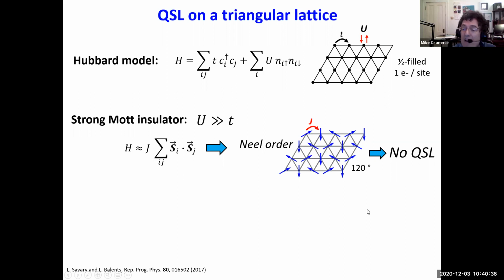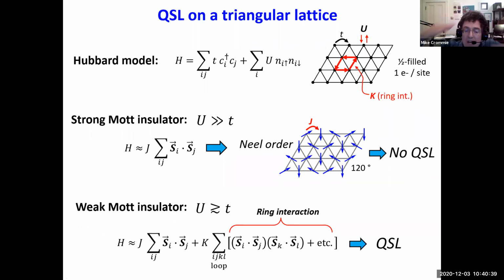On the other hand, if I reduce the Hubbard gap, make it smaller, so it's still bigger than t but not too much bigger, then there are going to be more interactions. I can think of more higher order terms in the perturbation expansion. In particular, you can get this interaction called a ring interaction, where these 4 adjacent spins all interact according to this little formula down here, and that creates additional frustration. That additional frustration then allows quantum spin liquid behavior to occur on the triangular lattice.